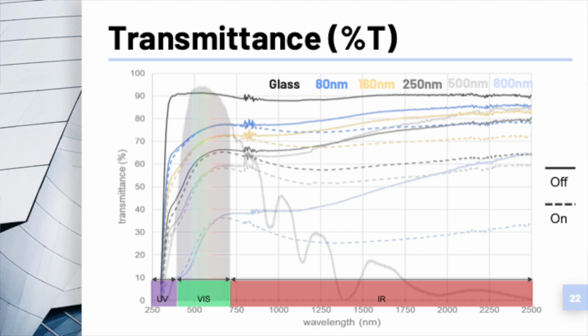And then overlaid onto the front of it are the different coatings that we developed. So a solid line is the coatings when they're off, a dashed line is when they're on. So you can see what happens is you've got a glass slide in black, and then you've got it with the different thermochromic coatings layered on, and you have more of that modulating capability as the coating gets thicker.